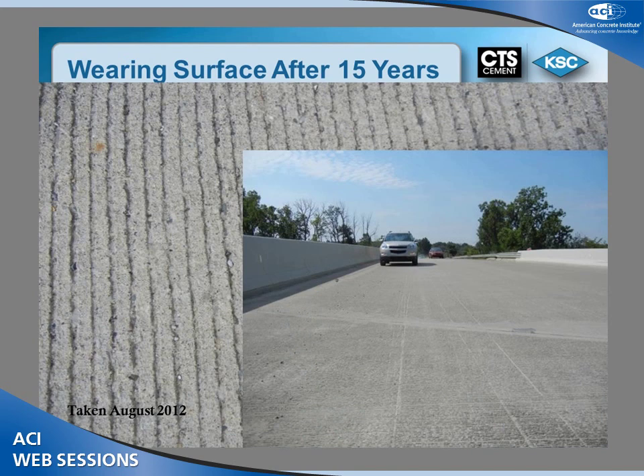When we get to the surface conditions of the concrete, we now start looking at 15 years of this concrete. What does it look like? If you take a Portland cement concrete deck at 15 years, you're starting to lose your tines. You're starting to see wheel ruts. Well, what's taking place here is, according to ACI 223, and also the knowledge that we have on shrinkage-compensating concrete, that water is contained within that cement, used up in hydration, so basically we don't get any bleed water. And because we don't get any bleed water, the water-cement ratio on the surface is the same as the rest of the concrete.